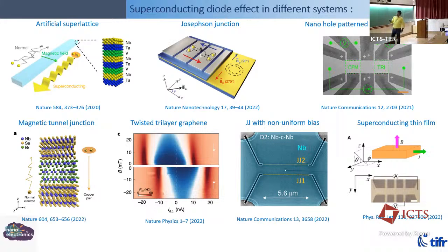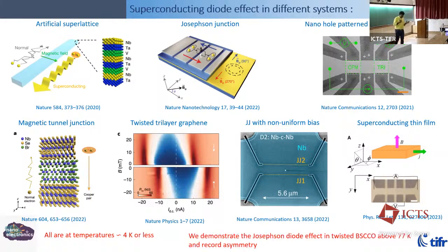People have broken inversion symmetry and time reversal symmetry in a lot of different systems by using a lot of different knobs. But the temperatures at which these devices work are millikelvin, and the asymmetry, which is the difference in the current that can flow in either of the directions, is a relatively very small difference. So in our work that I will show you with BSCCO, which is a high temperature superconductor, we can realize this kind of physics, and not just this, but more complex devices that I won't talk about today, at liquid nitrogen temperatures. And that opens up some interesting possibilities.